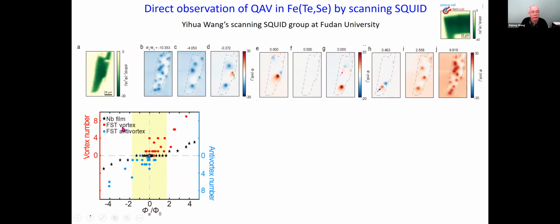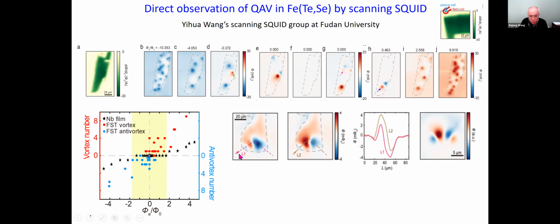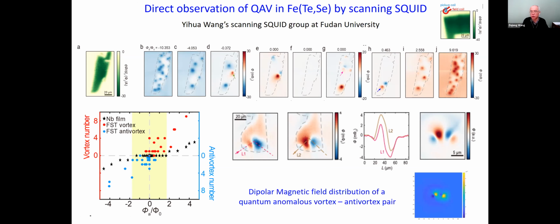Now, the circles are for FeTeSe. You do not need any external field, and they nucleate along the zero field line. And for small field, you have both vortices and anti-vortices. And of course, when the field becomes strong, you have predominantly vortex or anti-vortex. And the magnetic field distribution going along a vortex anti-vortex pair is shown here, which indeed exhibits this dipolar character of a quantum anomalous vortex when the magnetic moments of the magnetic ions are canted away from the vortices. So that's all I have to present today.